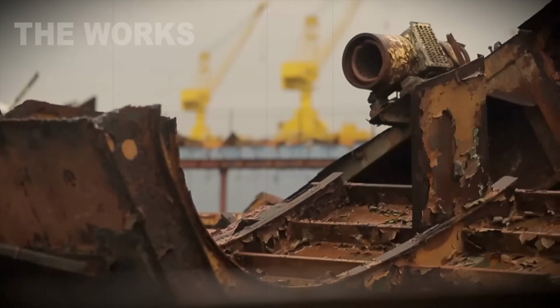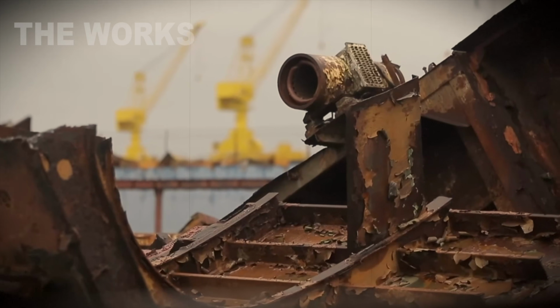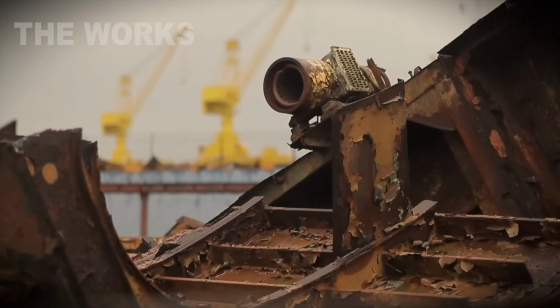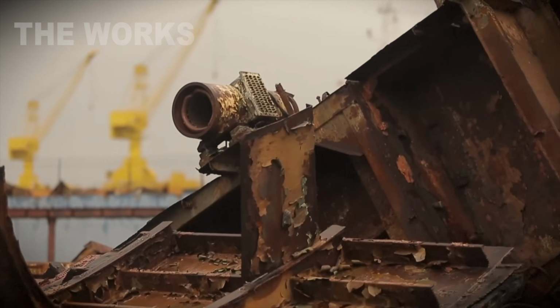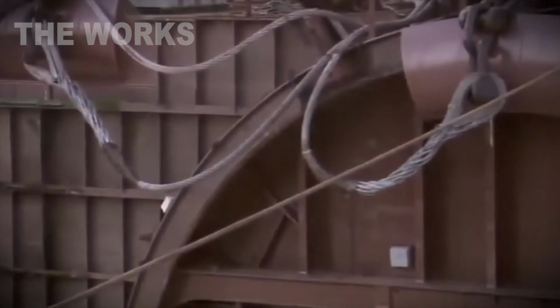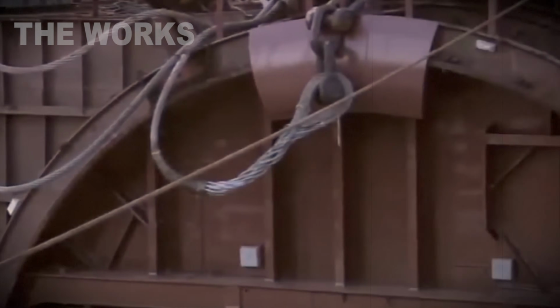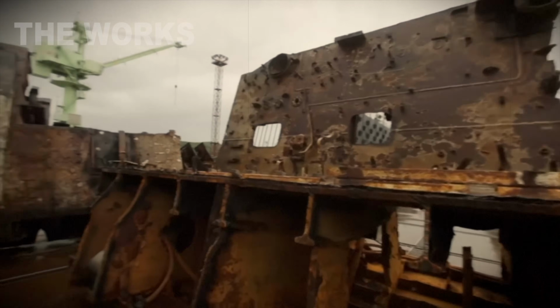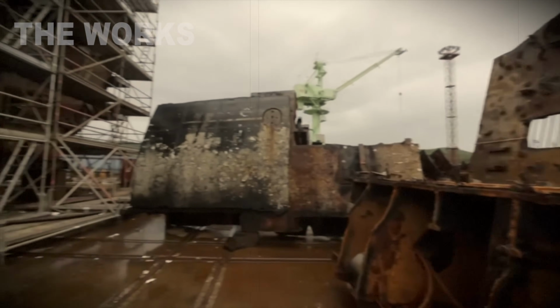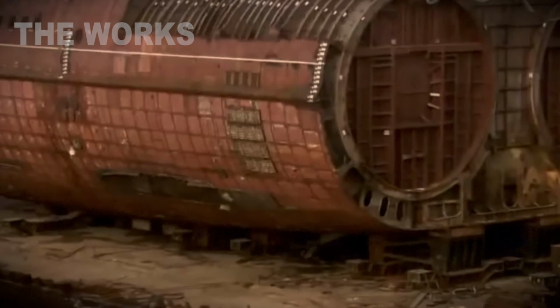The second tool, oxygen lances, a 10-foot steel pipe, 1-inch diameter. Inside, a bundle of steel rods, each about 1/6 of an inch thick. Pure oxygen flows through the pipe at 150 psi. Flow rate, 50 cubic feet per minute. The rods are ignited with an acetylene torch. They start burning in the oxygen.